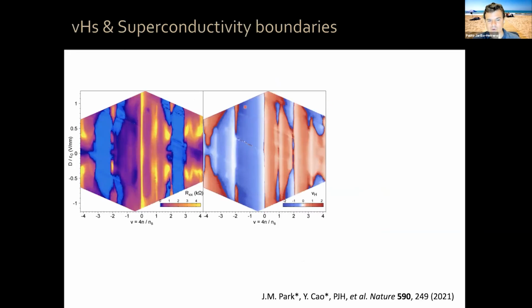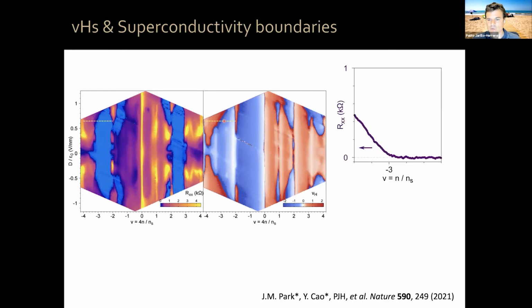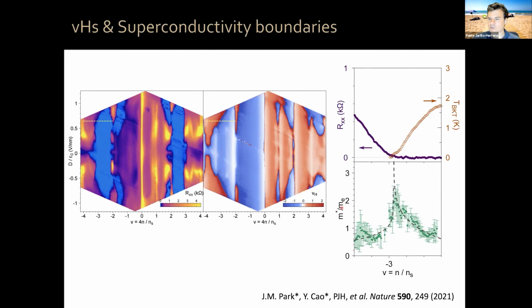So let's examine that a bit more closely. I'm going to show you trace cuts along this Van Hove singularity here, okay? So we can measure the resistivity, of course, in the superconducting state until it comes out of the superconducting state as I cross the boundary. I can measure the critical temperature as a function of filling factor. It's finite here, and then it's zero the moment it stops being superconducting, of course. Then I can also measure my effective mass, which is proportional to the density of states, as a function of filling factor. You can see that it diverges on both sides of this point. It has a cusp here and decreases on both sides of this point. That point corresponds to the Van Hove singularity, where you indeed expect your density of states to diverge, okay?